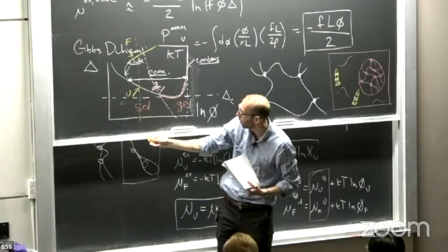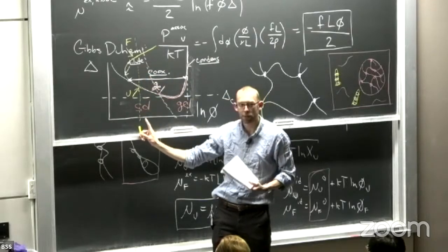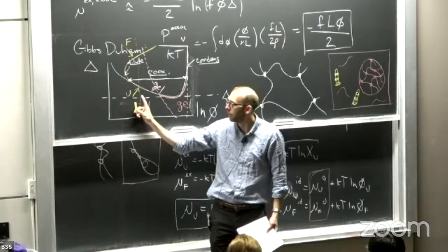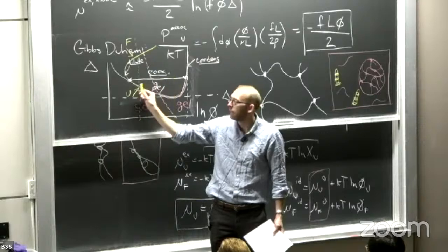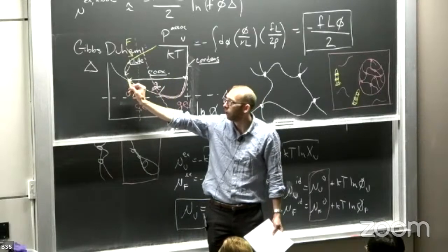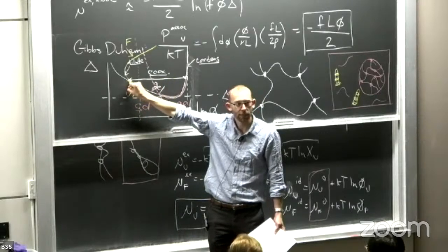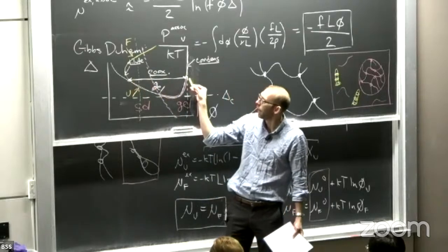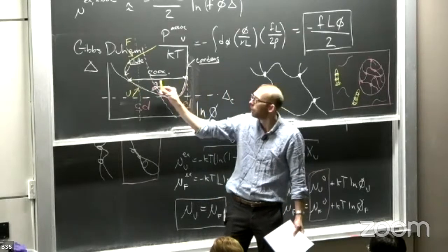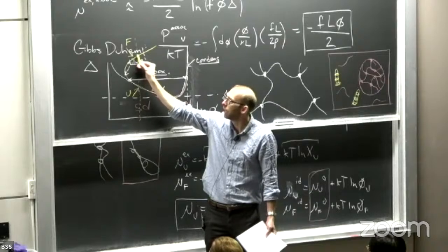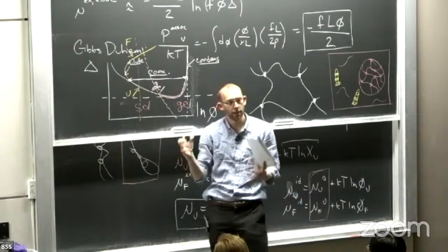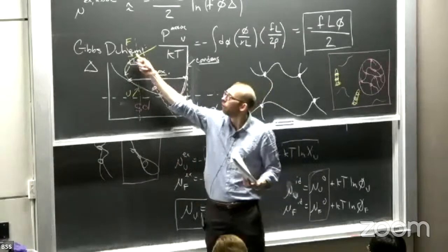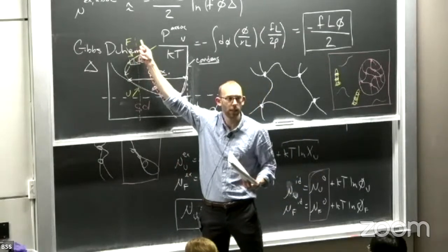So if I sit here at some polymer concentration, I initially start in a sol phase. I make my bond stronger and stronger. At some point, it phase separates into a sol low density phase and a droplet, that is my high density gel phase. And then if I keep going, eventually I end up with a single phase system again that is just these folded polymers in dilute solution.